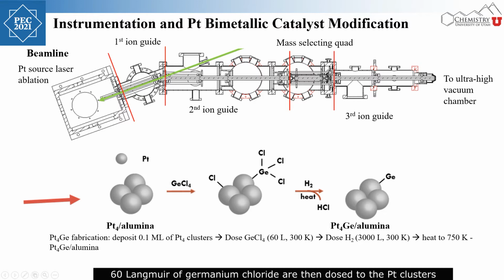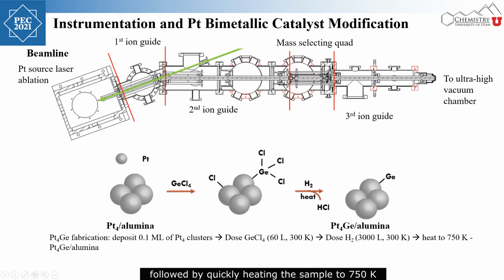60 Langmuir of germanium chloride are then dosed to the platinum clusters, and then chlorine atoms are removed by dosing 3000 Langmuir of hydrogen, followed by quickly heating the sample to 750 Kelvin. Samples with germanium-modified platinum-4 clusters will be labeled as platinum-4 germanium alumina in this presentation.